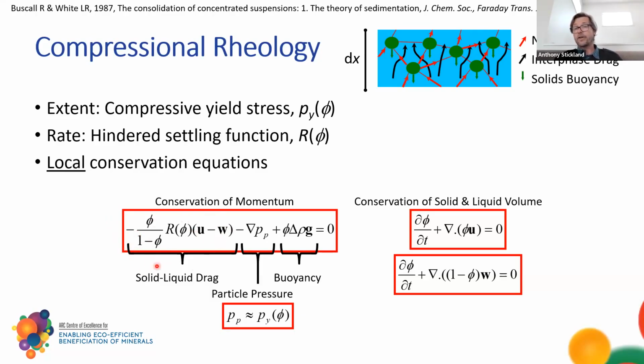It's got a term due to the solid-liquid drag, which is the difference between the solid velocity and the liquid velocity, scaled with some drag factor. R of phi is what's called the hindered settling function, and it changes as a function of concentration to describe the drag. There's a gradient of the solids pressure, or the particle pressure, and as long as the pressure is increasing or constant, we can assume that particle pressure is represented by the strength of the material. If I start releasing the pressure, then we've got to worry about elasticity of the bed and various other things, so that doesn't always hold.